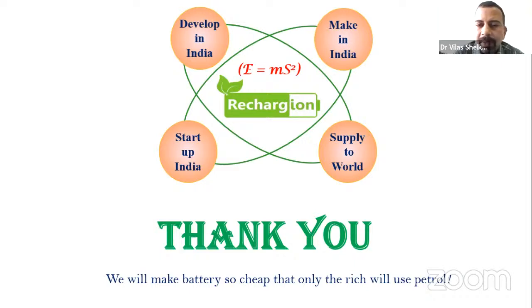But now there are quite a few companies venturing into the manufacturing of lithium-ion batteries. The good thing is that the same assembly line used for lithium-ion battery manufacturing can be used as it is, without any change, for sodium-ion battery manufacturing. Everything will remain the same. There is no change in pouch cell fabrication, electrode coating, or sealing. The entire assembly line, from start to the end deliverable, will be the same for lithium-ion and sodium-ion batteries. Only when you make the powder and the slurry, instead of lithium-based material, you will use sodium-based material. Otherwise, everything will remain the same.